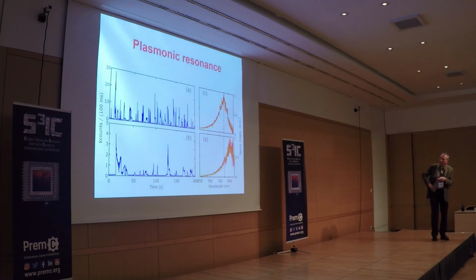So you see here a trace as a function of time, for this plasmon, for example, in which the laser at 770 was really resonant with the plasmon. You see very bright two-photon signal traces, where the different intervals are due to one quantum dot landing on the surface, emitting photons, and detaching. So this is not bleaching, it's really detaching. This we know. And this is a different plasmon. If you are not as well centered on the plasmon resonance, it's a bit on the wing, you see that the bursts are much weaker, about a factor 10 weaker.